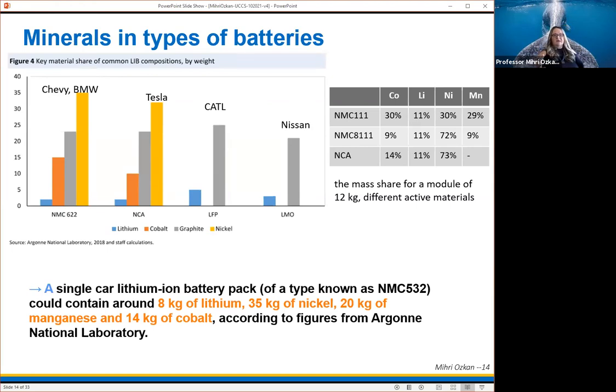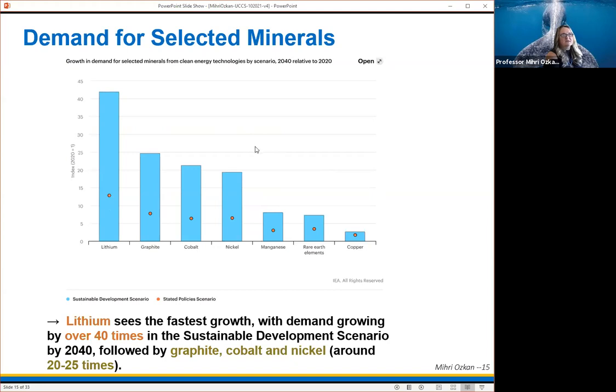So if an EV is made with NMC 532 battery packs, only one car contains around 8 kilograms of lithium, 35 kilograms of nickel, 20 kilograms of manganese, and 14 kilograms of cobalt. So imagine that this is only one car. And then we know the projected number of EVs, and this is going to be a huge demand on these minerals. Indeed, the projection to 2040 shows, for lithium, demand growing over 40 times. And for graphite, cobalt, and nickel, about 20 to 25 times because of the rush in EVs.